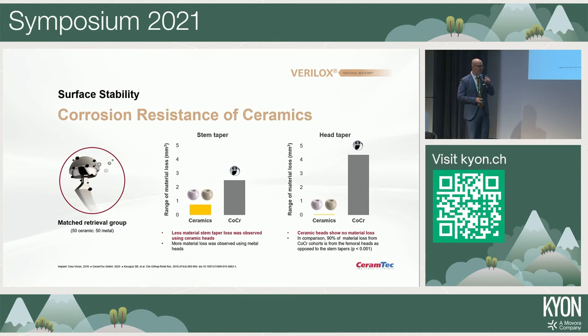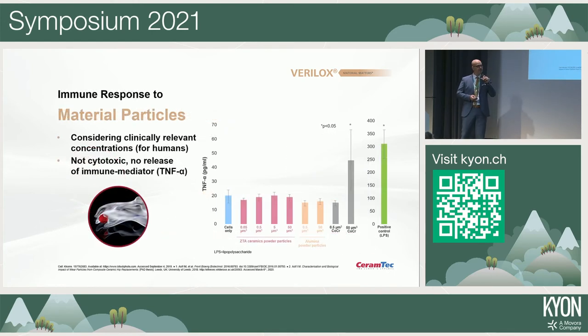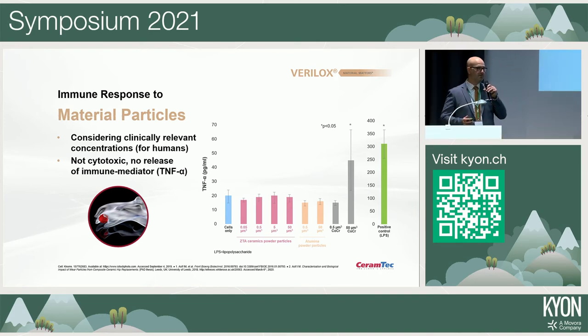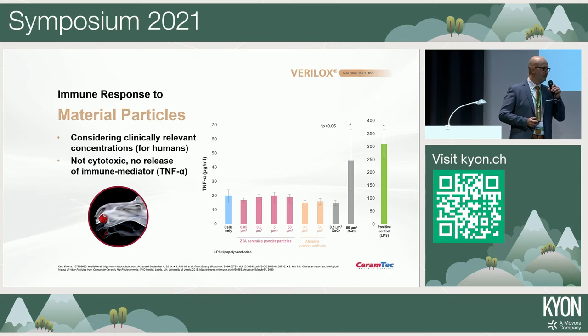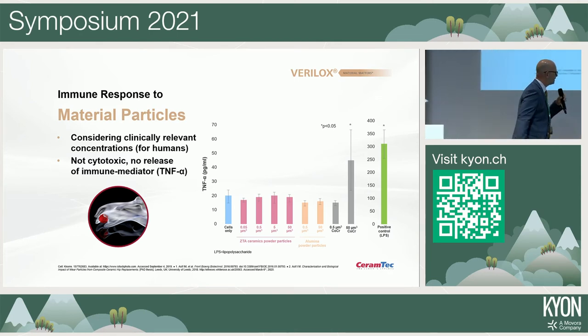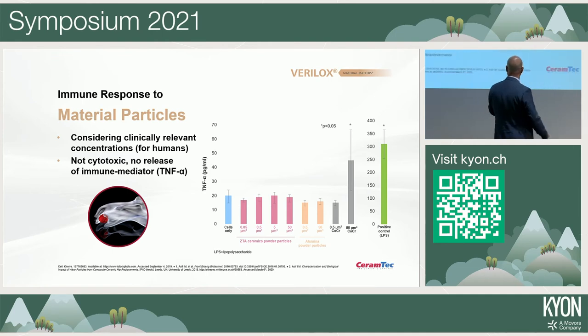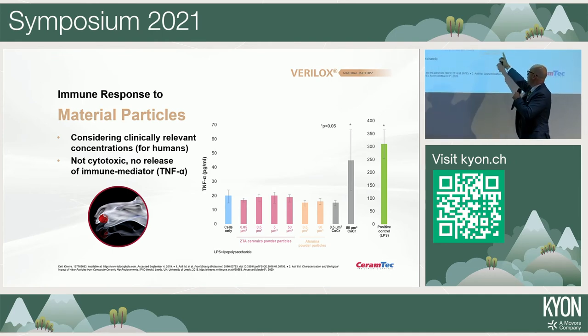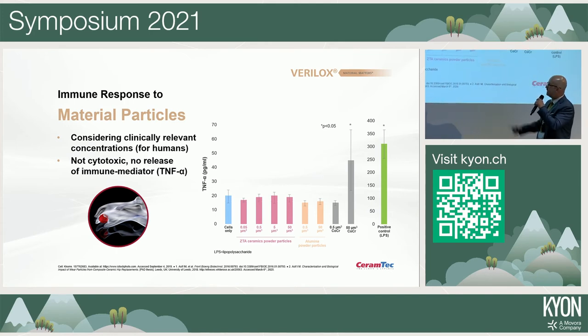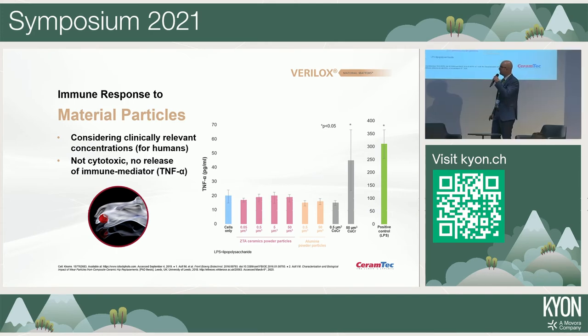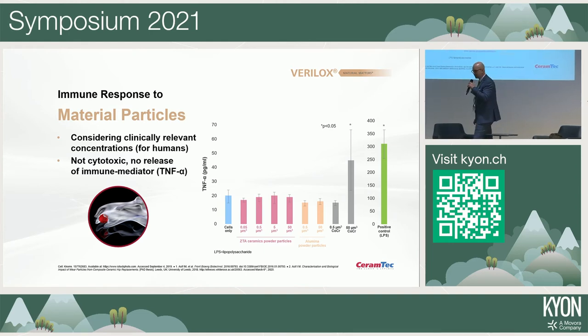But what happens to the particles if they are released to the human body? And also for these things, you can do tests. And this is a study which we did with the reaction from human cells to debris in an amount which is comparable, from the assumption, with the amount of particles that could be released in the human body. And what you see there is the release of the immune modificator TNF-alpha with our ceramic particles is in the same range as if you test the cells alone, while if you use the cobalt chromium particles at a certain threshold level, you get definitely a reaction of the cells.